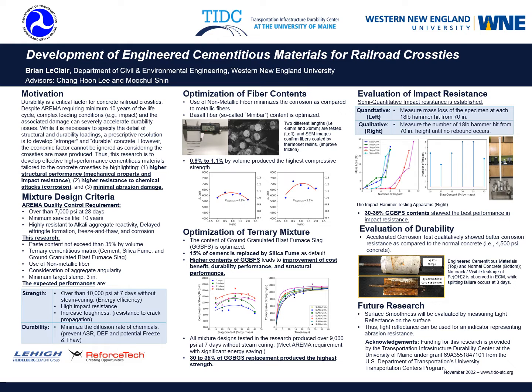Next, in the top right corner, we wanted to evaluate the impact resistance of the samples based on their slag percentages. First, we developed an apparatus to impact the samples in a consistent way. This can be seen in the picture on the right. Basically, it is a long PVC tube that we drop an 18-pound metal bar down to hammer the sample underneath. After we did that, we had to develop a way to compare the samples and how well they resisted the hammer impact in a quantitative and qualitative way. To do this, we developed two methods.